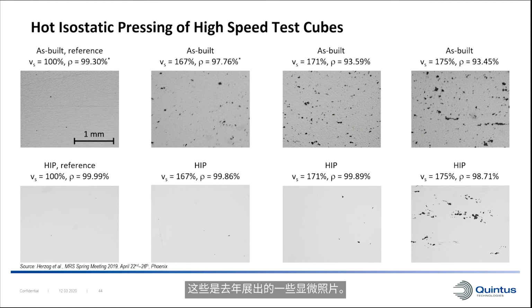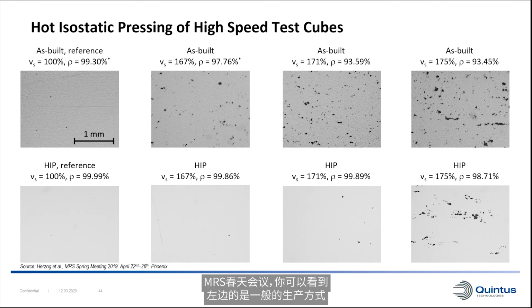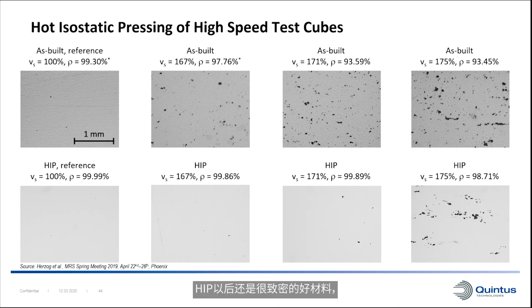And these are some micrographs presented last year at the MRS spring meeting. And you can see here on the left is the normal way of producing with as dense as possible material. And this, of course, after HIP is still very dense and good material. But by increasing the laser speed by 67%, the density drops to around 97.75%. And after HIP, it's completely closed again. The same goes for 171%, or 71% higher laser speed. And here you can see that the density drops off a little bit to around 94%. And it can also be closed with HIP.